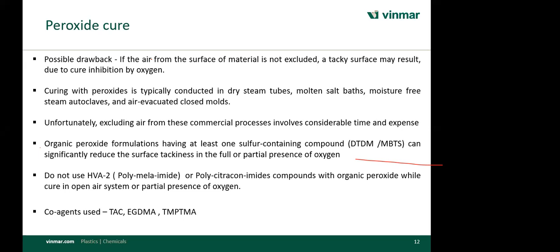The only culprit here: don't use HVA-2 type of co-agent like poly-maleimide or poly-citraconimides. They are not recommended as a co-agent for peroxide system. What happens, I found in industry, a lot of people, when they use peroxide like Dicup or some Perkadox 14-40, and from where they get this peroxide, immediately their supplier tries to push HVA-2. And so they are giving the complaint: my compound is not cured properly, or I am not getting the desired properties. So please remember,